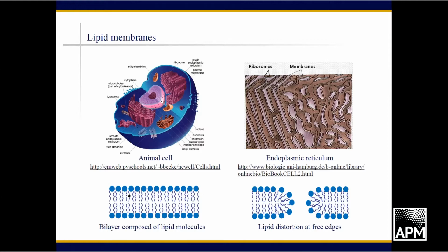So essentially, the lipid bilayer is a thin liquid crystal film. If we try to bend the surface, so imagine this interface between the two leaflets of the bilayer as a mathematical surface, then we cause a splay in the liquid crystals, and this is energetically costly. And so in effect, the surface has a bending resistance like a shell, except that the shell has a liquid-like property.